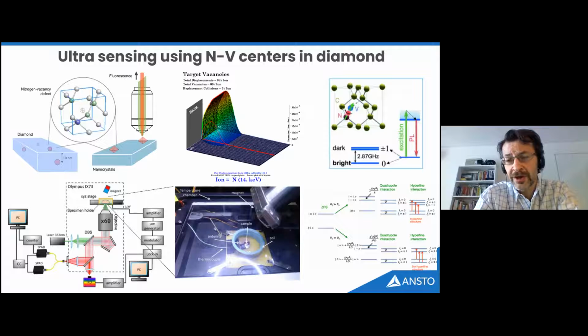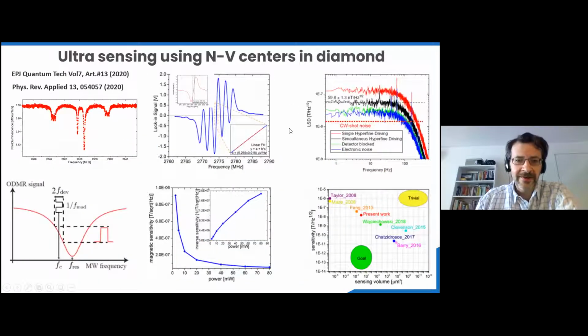And we can use optically detected magnetic resonance and radio waves in order to excite the nitrogen vacancies into the higher state, and then we observe the transition into the lower state. And by observing these transitions between the states and the shift because of the presence of magnetic field, we can create a very, very sensitive magnetic sensor.